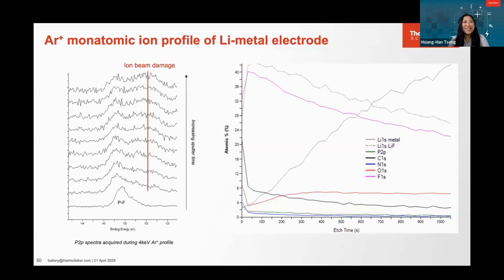Thank you very much. So now I'm presenting a battery sample from MEET at the University of Münster in Germany. It's a lithium metal electrode and has already been cycled. Our goal is very simple. We want to understand the chemistry of the SEI layer formed on top of this electrode. So there's no other way. We have to do the profile through the layer all the way to underneath to the underlying metal electrode.